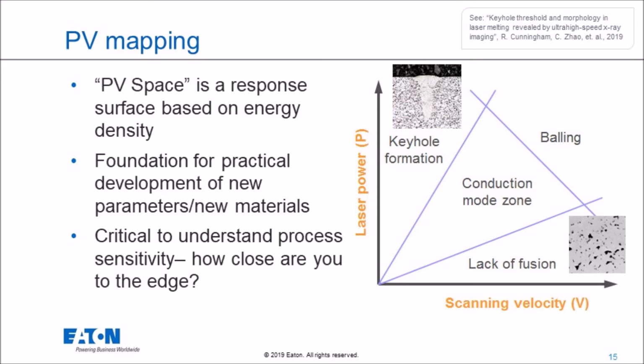And you want to build as quickly as possible. So most people will try to have their parameter set around here, right? Which is great, because then if your laser power changes 1%, you're still within that good zone, right? But if you're running a parameter set and you're not sure where you are, and you're near the edge here, and your velocity changes because your galvanometer does something wrong, well, now you're creating keyholes in your part.